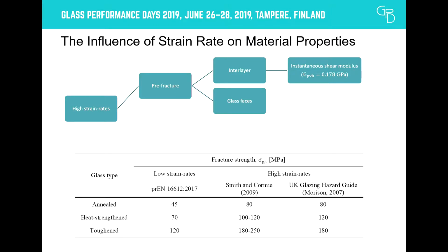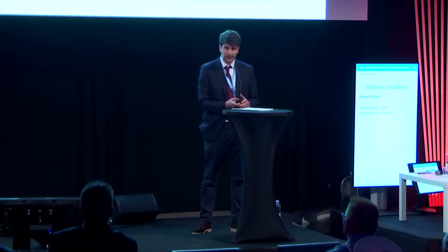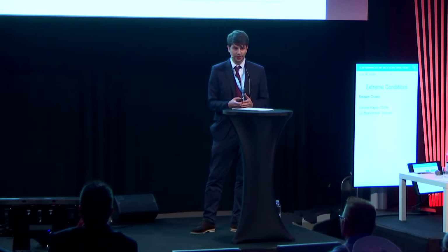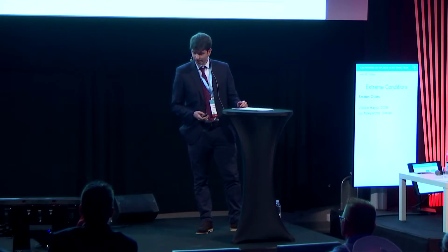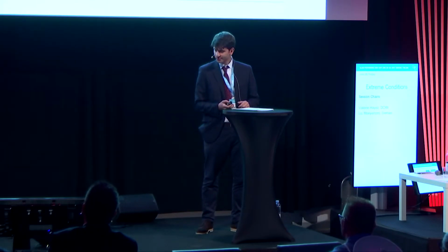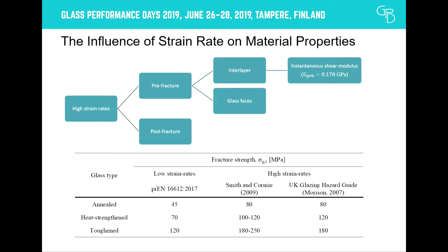This has been observed both experimentally from multiple blast tests that have defined higher fracture strength values, and also demonstrated analytically by extrapolating the low strain rate values to high strain rates using Boltzmann's integral. In the post-fracture response, the behavior of the interlayer is affected by the attached glass fragments, resulting in a stiffening effect.